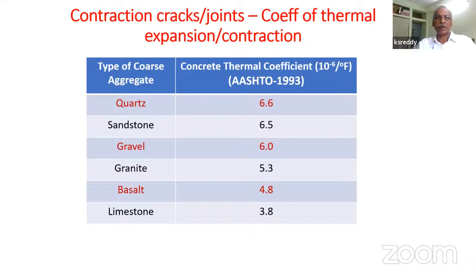on the spacing at which the cracks would form if there are no joints created, or the spacing of the transverse joint that we need to create. That has to be significantly dependent on the type of aggregate that you want to use. For example, many agencies elsewhere, let's say in the US and other countries, if they are using limestone aggregates, they recommend a spacing of almost about 6 meters. On the other hand, if these are quartz aggregates, the spacing would be as low as 4.5 meters. 4.5 is what we use in India, typically, for transverse joint spacing. But if you are using limestone aggregates in your concrete, your spacing of transverse joints can be increased to as large as 6 meters.